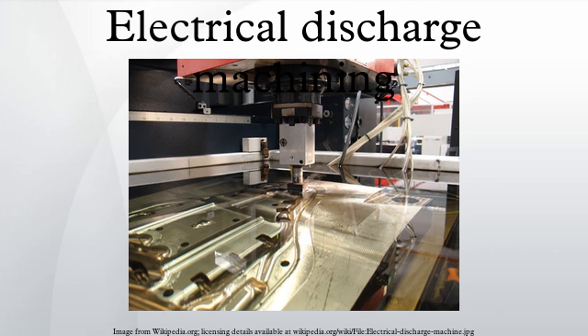These models give the most authoritative support for the claim that EDM is a thermal process, removing material from the two electrodes because of melting and/or vaporization, along with pressure dynamics established in the spark gap by the collapsing of the plasma channel. However, for small discharge energies the models are inadequate to explain the experimental data. All these models hinge on a number of assumptions from such disparate research areas as submarine explosions, discharges in gases, and failure of transformers, so it is not surprising that alternative models have been proposed more recently in the literature trying to explain the EDM process.